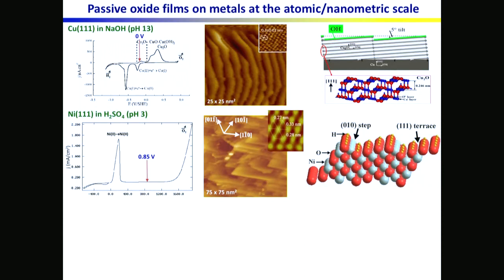growing structure. But if we added a small amount of water to the oxygen, water vapor, then we found this structure. So a small amount of water vapor in the gas will result in the same growth of the oxide as in aqueous solution in that case.